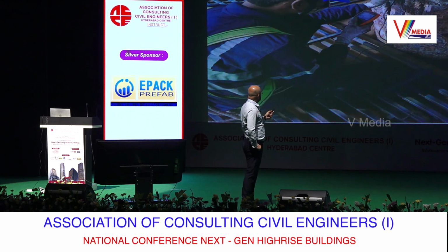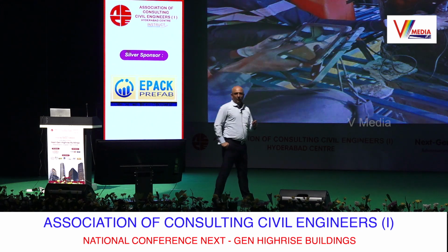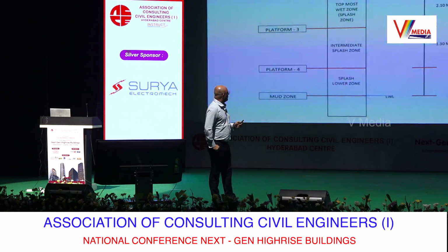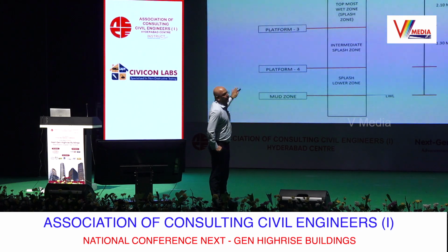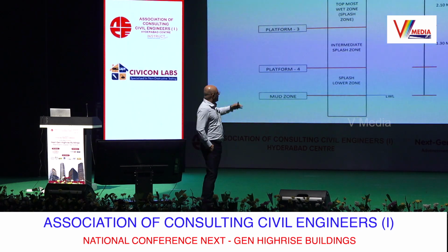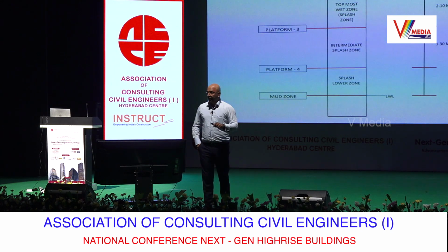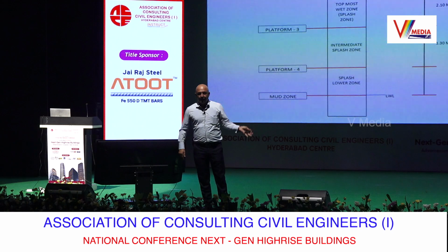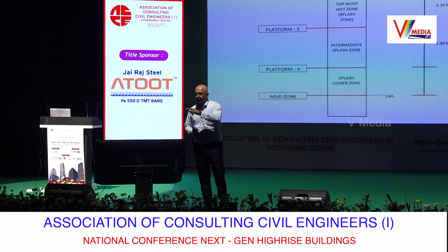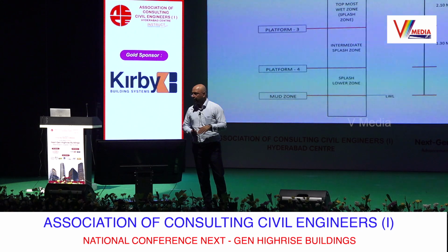Then core extraction was done, steel thickness testing was done, corrosion testing was also done, half cell potential and other things. And these were the overall zones that we divided, to see what was getting damaged. So we realized that the splash zone was the zone which got more damage, but surprisingly, because this is in Dahej, and there the tidal variation is almost 9 to 10 meters, and also the wave velocity is very high.